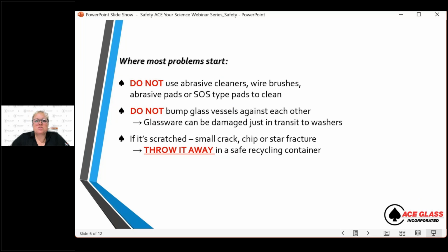Most problems start, believe it or not, when we clean our glassware. And the biggest issue is that a lot of people try to get some gunk out of it and use wire brushes or abrasive pads. Or it just happens that you have your glassware in the sink and you clean it and you bump it a little bit on the edge of the sink. And overall, that can very easily cause tension in the glassware.